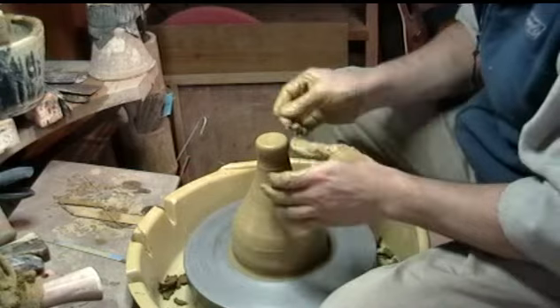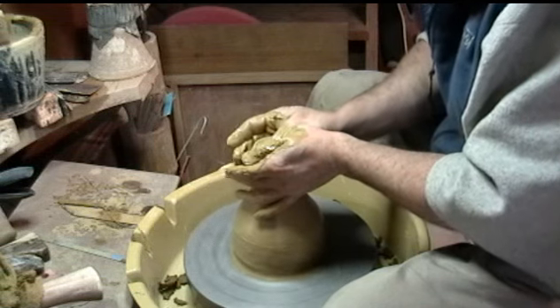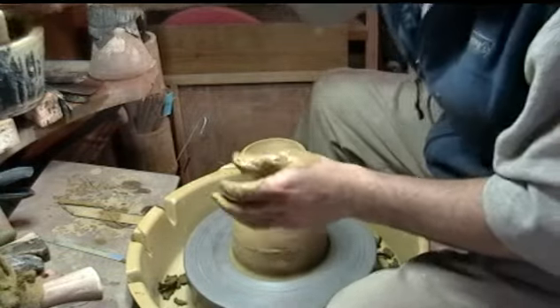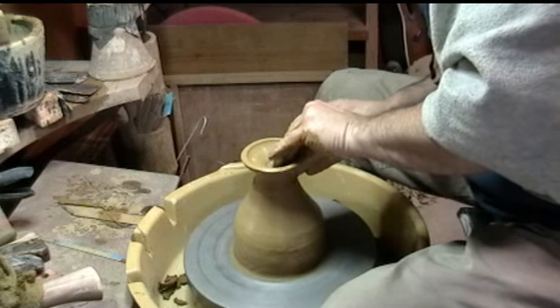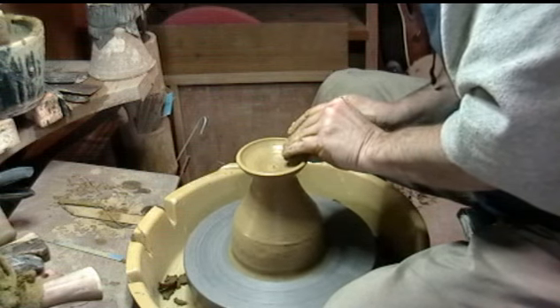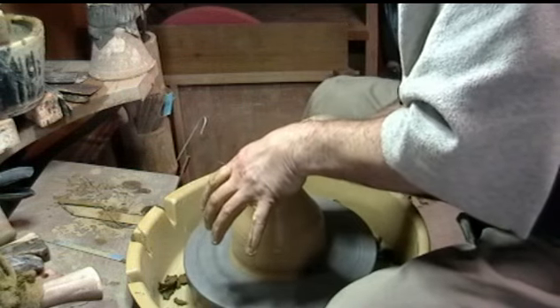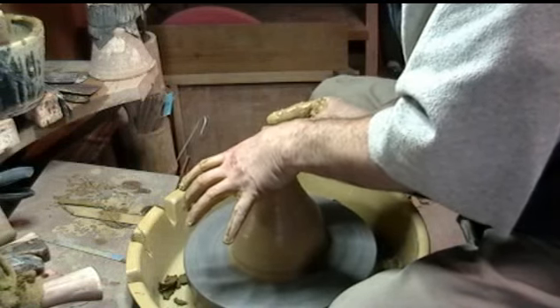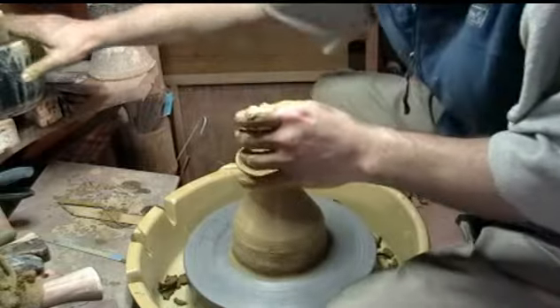You get a little wobble in the top of the clay. It's not that important with things this small. In fact, sometimes it makes for a more interesting little cup in the end. You can see probably I'm using slip to wet the clay rather than water, because this is a really open sandy clay body, and if you throw off the hump like this with water with this stuff, then by the time you get halfway down the hump you've got a big pile of sludge that doesn't hold its shape anymore.